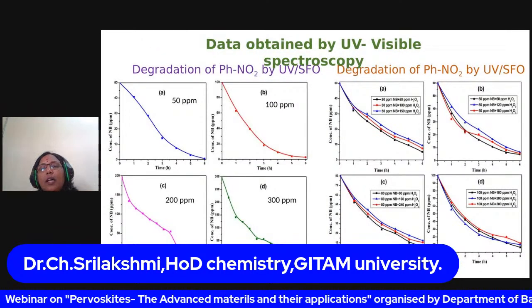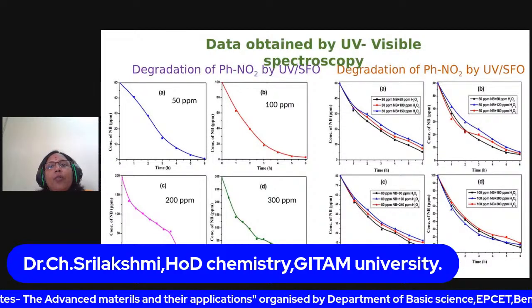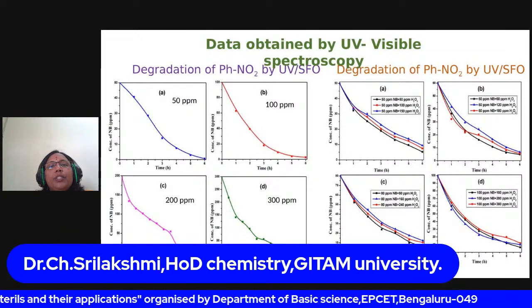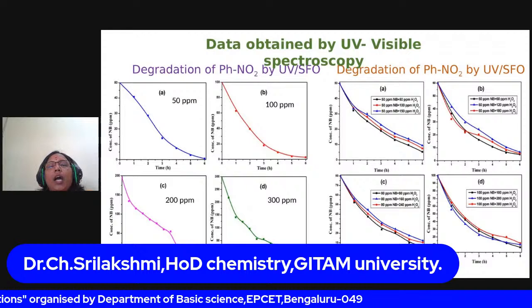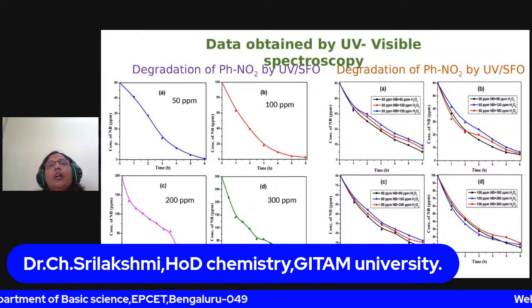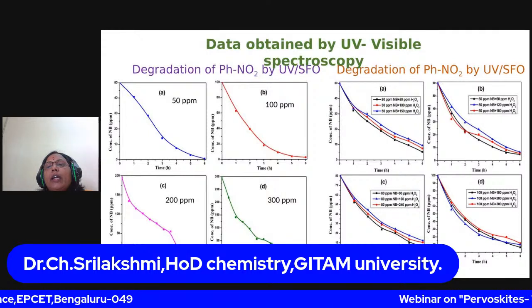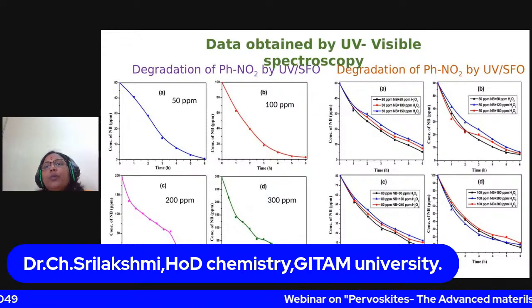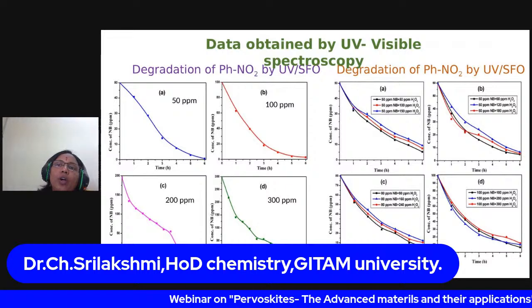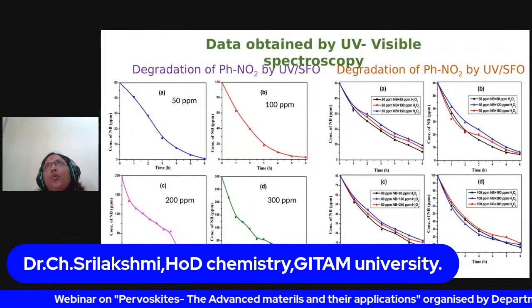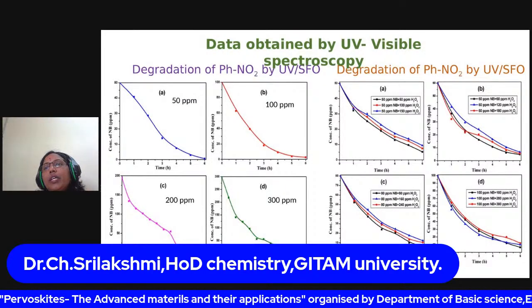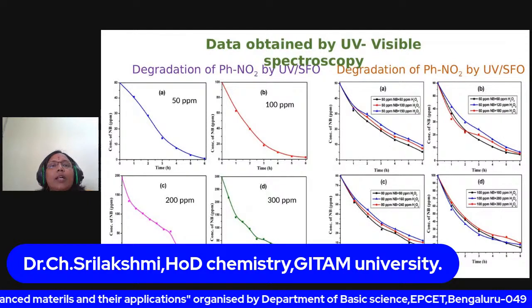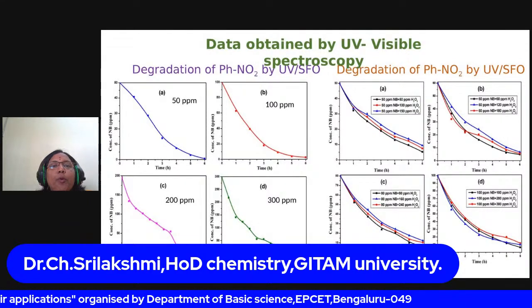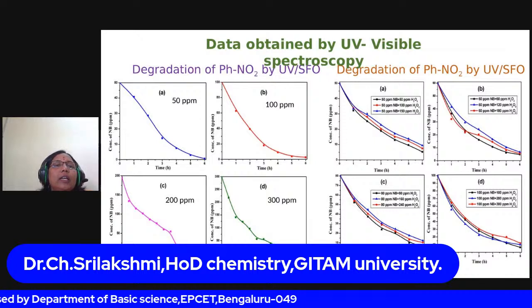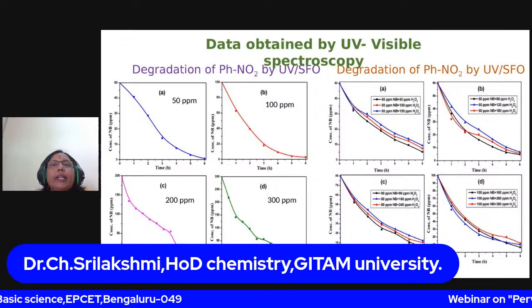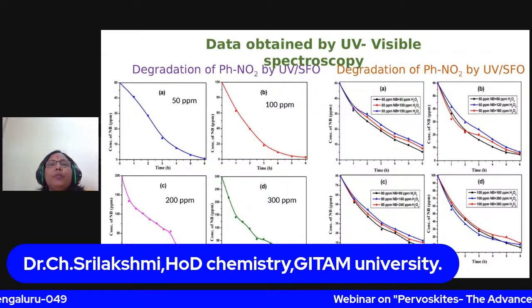So these are the profiles, you see. We have conducted it in two ways: degradation of nitrobenzene using UV and the catalyst, that is strontium ferrite, and also UV and strontium ferrite with H2O2 as an oxidant, and in the absence of oxidant, just UV and the catalyst. These are the profiles we have created from the data obtained using UV-visible spectroscopy.